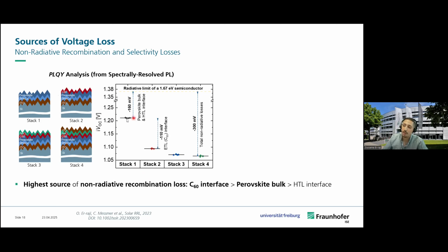And then by comparing this to the radiative limit of a perovskite with this band gap, so the band gap of 1.67 in our film, we can extract the losses which are due to the non-radiative recombination in the bulk and at the interface with the HTL. And this was assessed to be 160 millivolt. In the second step, by adding the top interface, so the C60 interface, we assessed an additional loss of 110 millivolt. And so by adding the different functional layers, we found that the total amount of non-radiative recombination was 300 millivolt.